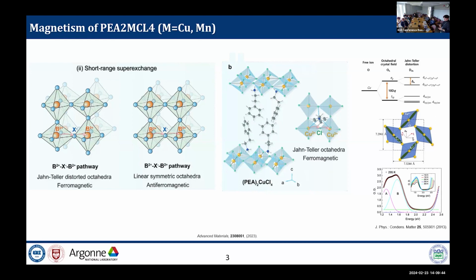Additionally, more distortion due to some hydrogen bonding, then the orbital splits into five different energy states. In this case, copper has a d9 electron configuration, with nine d electrons. So in the ground state, this makes a hole state in the octahedral, especially in PEA2 copper tetrachloride, which has an ordered hole orbital state in the dx²−y² or dy²−z² orbital.